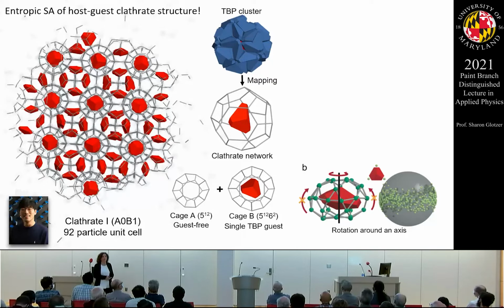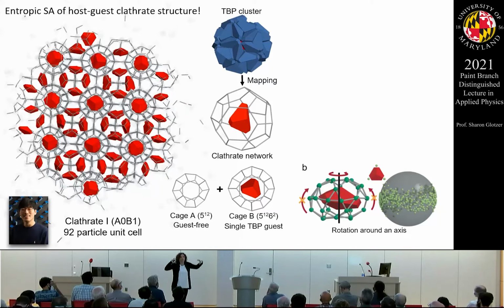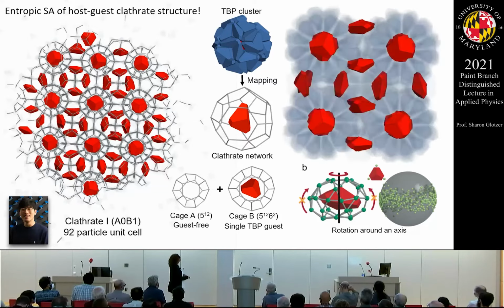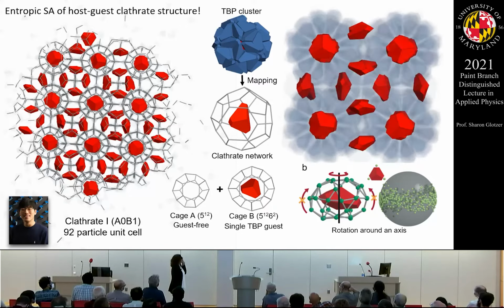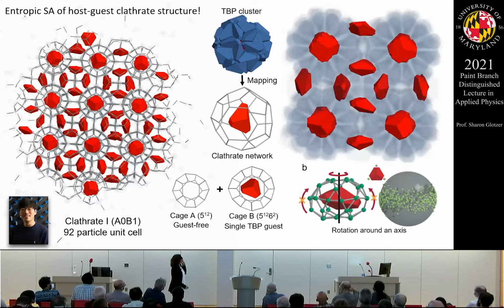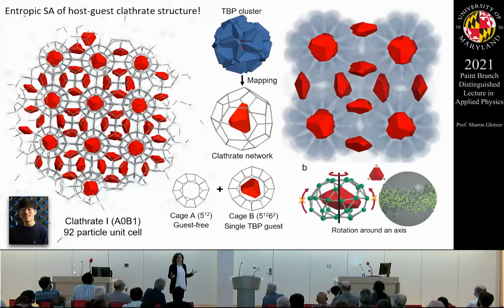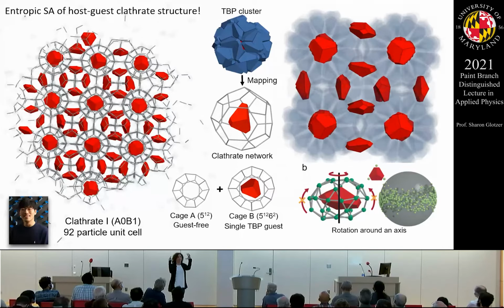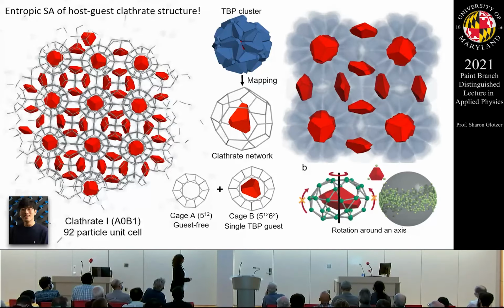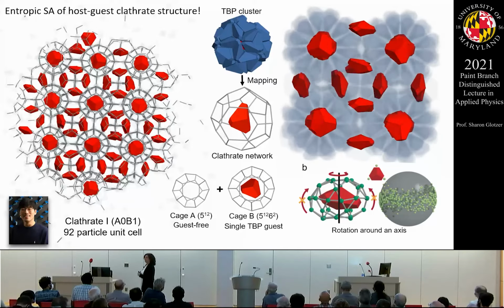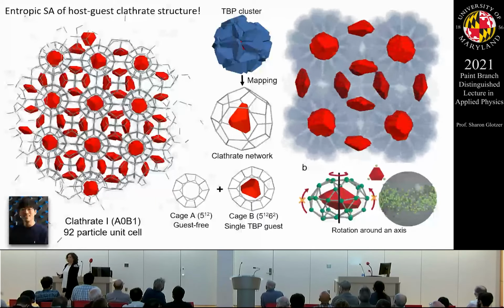It's got 92 particles in the unit cell. It's a guest-host structure where the guests are the hosts. It's the same particles, right? The system is forming this clathrate structure and then sequestering inside one of its own. And the reason that it does that, you can see here, the whole cage structure, the host structure, is basically locked up, very little entropy. It's dumped all its entropy into those guests that are spinning around like crazy. If you don't let them spin, this structure falls apart.